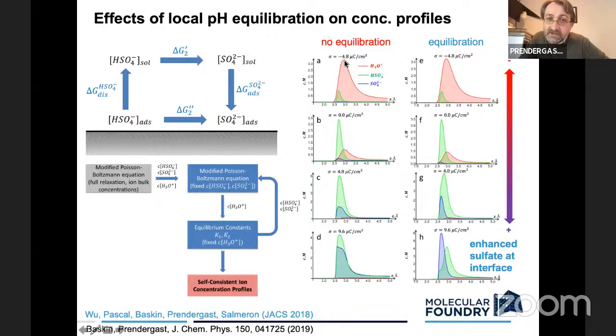If it's a negatively charged surface, obviously those positive ions will be drawn to the surface. And as you go to positive charge at the interface, you're driving those hydronium ions away. And actually there's no hydronium near the interface. It sits at about 3 angstroms out, actually here in the equilibrated phase. And it's basically at its bulk concentration. I hope that answers your question, but the answer is it depends on your distance from the electrode surface.